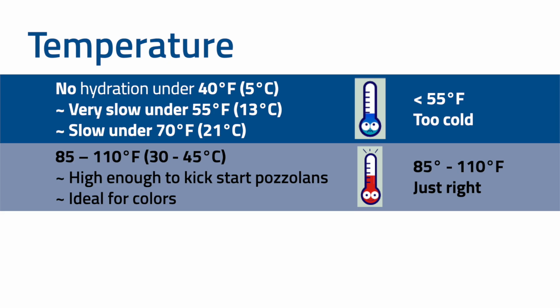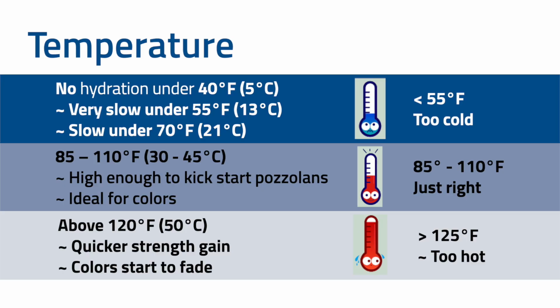You may ask, when will cement hydration not occur? This happens when units freeze before they are properly cured. The chemical reaction is compromised and the units will never harden. On the flip side, units that are exposed to over 125 degrees Fahrenheit will gain initial strength very quickly, but the hydration reaction will not be complete and the units will not reach their full potential strength. At high temperatures, colors are affected and often start to fade.